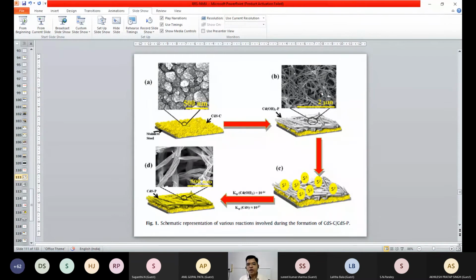Initially we have deposited cadmium hydroxide. How have we deposited cadmium hydroxide? We have taken ammonia and a cadmium source, which may be cadmium nitrate or cadmium chloride, so that you can end up with cadmium hydroxide nanowires on the substrate surface at just room temperature. At just room temperature, right? So this is cadmium hydroxide. So how have we made cadmium sulfide from cadmium hydroxide? Chemistry people can understand it in a better way.